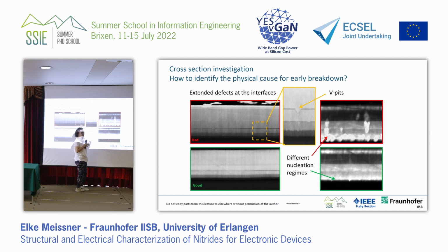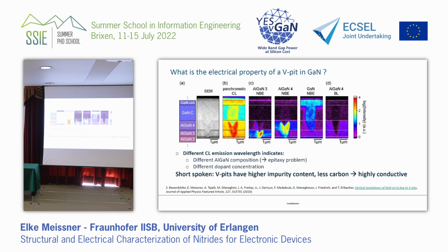We said by definition: are there many V-pits? Do we need the V-pits? Can we be angry about the V-pits? We don't like them. Because the V-pits, and I can show you, they collect impurities. And this is what we don't want. V-pits are relatively large, much larger than a dislocation. And if you observe them all here, they collect dislocations, they collect impurities, and they collect dopants.